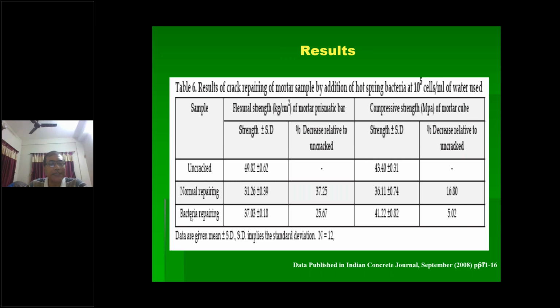Now the same cracks have been repaired with bacteria. Then what we are getting in these cases, this value has been slightly increased, that is 37, but it is not up to the uncracked condition. So we are getting a percentage decrease with respect to this. In this case it is 37 to 25. So there is an improvement in such a sense, you can say.